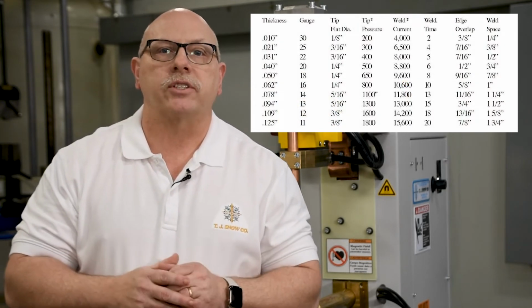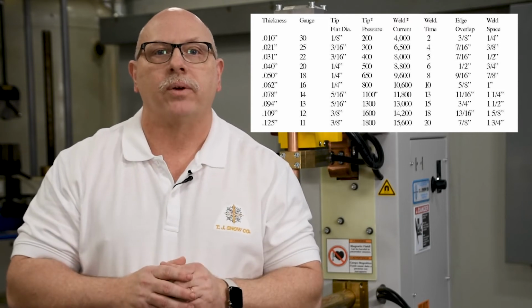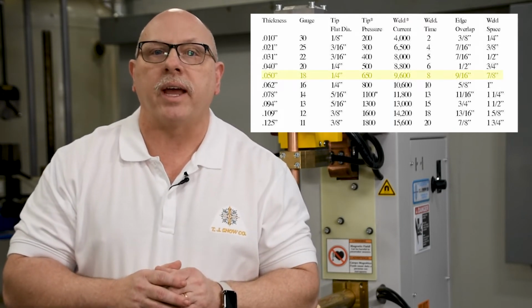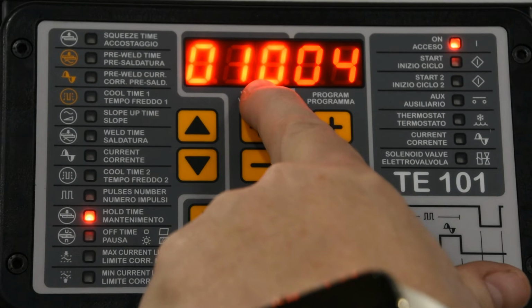We should already have the squeeze function at its maximum value. The recommended weld time for 18 gauge mild steel is 8 weld cycles. Depending on your control's feature set, current may be programmed in amps per the chart callout, 9,600 in this case. However, I recommend starting at around 10% below this value and then increasing from there based on weld tests. Now, if you are programming in percent current, also known as heat percent, set this value at 50% to start. Hold time will be set to 10 cycles.